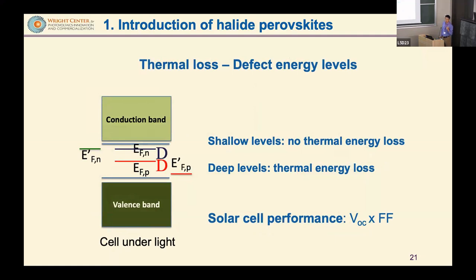So the splitting, if we do not consider the non-equilibrium condition, will usually reach close to the bandgap. It can be smaller only when the generated electron-hole pairs are fewer than the photon density, which is caused by the defects. Okay.